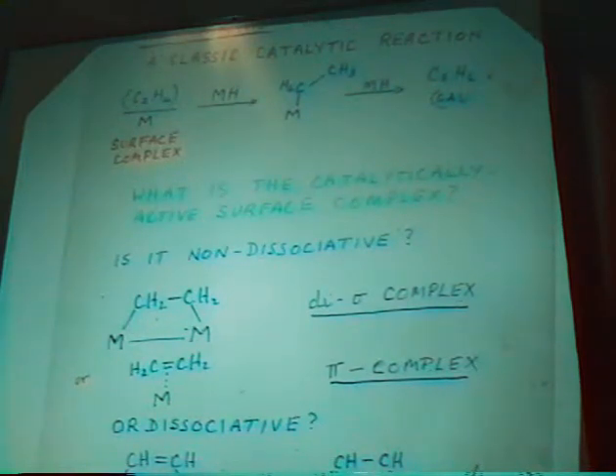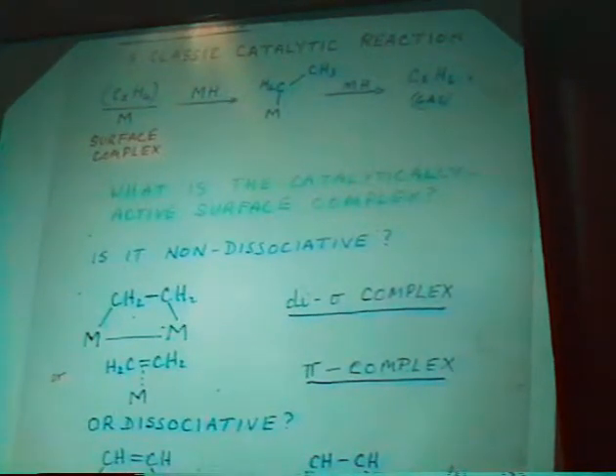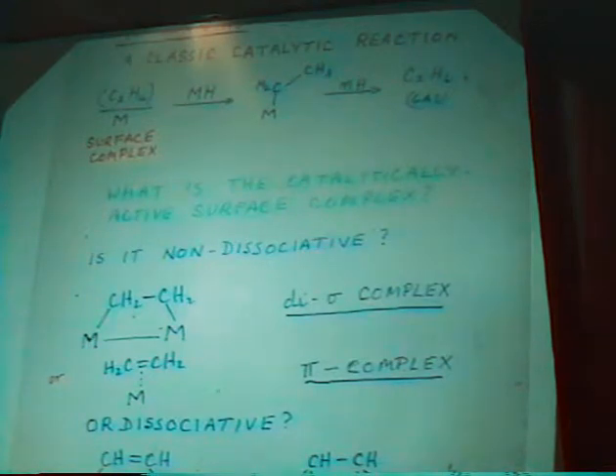But it was also known that very often when you put ethylene on a catalyst, first of all, you got some ethane off. There had to be some dissociatively adsorbed species present, which might be something of this sort or of this sort. But in principle, by infrared spectroscopy, we could at least distinguish the ethylenic type species from the alkane type species. And so we set to work to see what we could find.